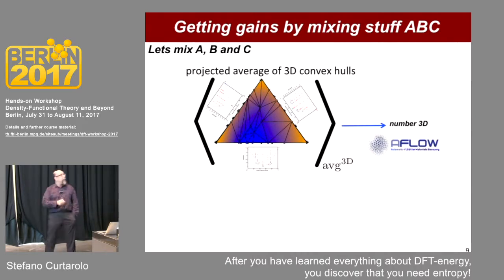Anyway, you go on the database, because we have calculated energies for almost 20 years, and you get all the possible ternaries. We have got like 15,000, and you get a number which is pretty much the expected number of mixing enthalpy if you create a ternary. This is just a number. Then, of course, you have limited data, but you trust what you have, all right?